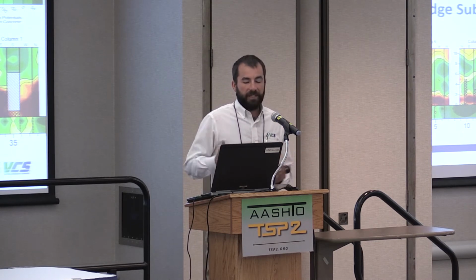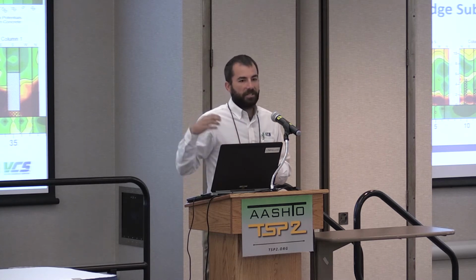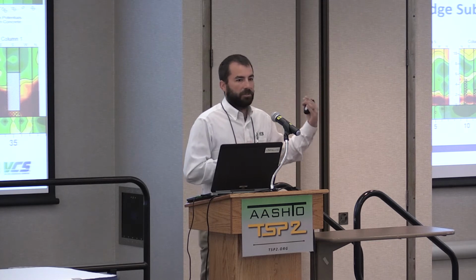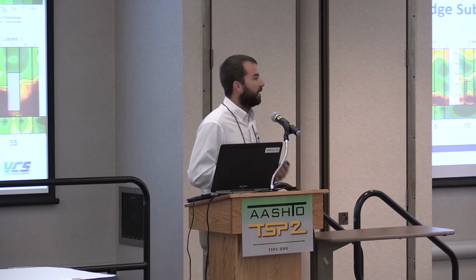So while they have effectively the same exposure, that lower column area and the footer, the chloride progression hasn't reached the steel in the footer where it's reached the steel in the column. So cover depth affects the service life, and we're seeing that here where the corrosion is active currently. Maybe we do something preventative on the footer to prevent corrosion from starting, or maybe we just leave it and say, oh, we've got some years before we need to address this.